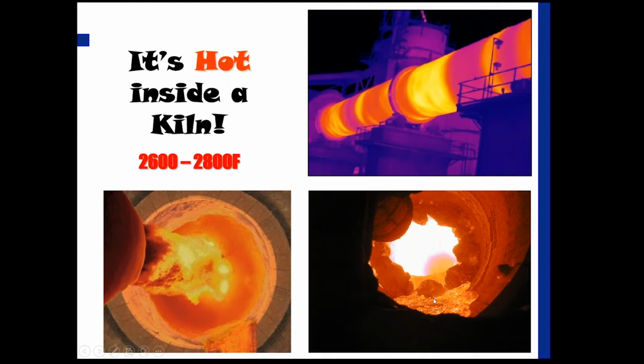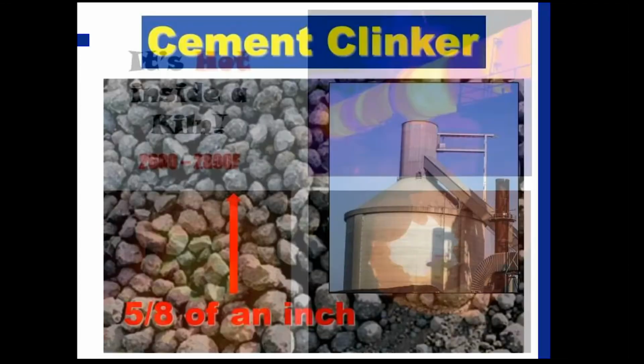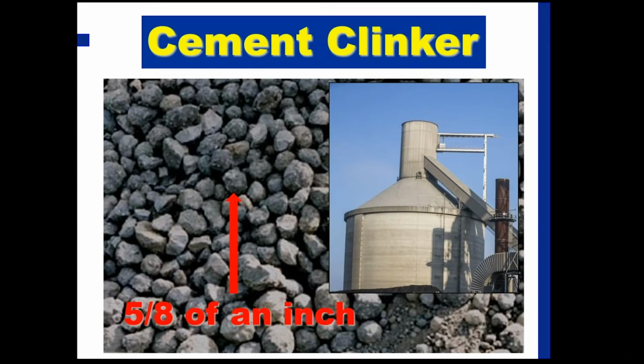And basically what we've done is disassociate all the chemical elements into their free nature. And so now we're going to see some recombining of that as this material solidifies after being melted. And so when clinker comes out of the kiln, it passes through a cooler, and that cooler tends to kind of freeze or lock in the silicate mineral growth. We don't want those minerals to grow too big because we want the reactivity from a smaller, well-defined clinker crystal, a silicate mineral. And so when we're looking at clinker, typically 5/8 of an inch, the old guys at the plant will tell you that's kind of an ideal size for a clinker nodule.